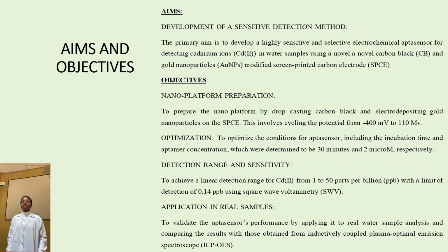Thirdly, we have detection range and sensitivity: to achieve a linear detection range for cadmium from 1 to 50 parts per billion with a limit of detection of 0.14 parts per billion using square wave voltammetry. Last but not least, we have application in real samples: to validate the aptasensor's performance by applying it to real water sample analysis and comparing the results with those obtained from inductively coupled plasma optical emission spectroscopy.